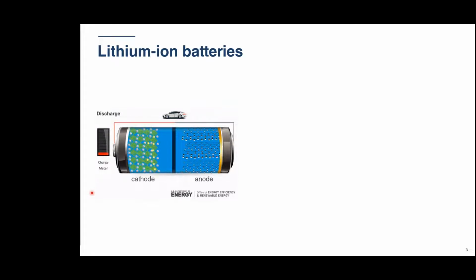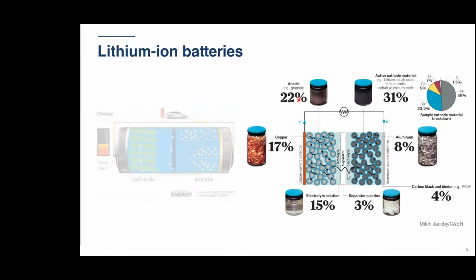But there are many components that make up a battery, so not just the active anode and cathode materials, but we also need metal foils on both the electrodes, and then we have the electrolyte, the separator, and then also normally a carbon black and a binder material. So if we consider just the active materials, the anode is typically based on graphite, and the cathode material contains lithium and cobalt. And these are geopolitically compromised materials. They're concentrated in the globe. And the question is, do we have enough of these materials for our projected future consumption?